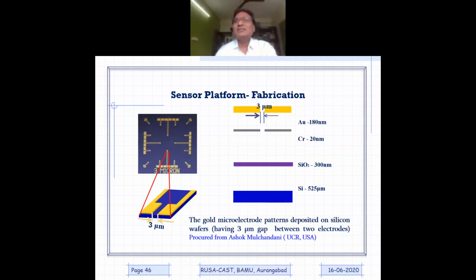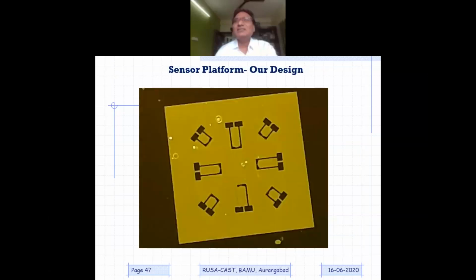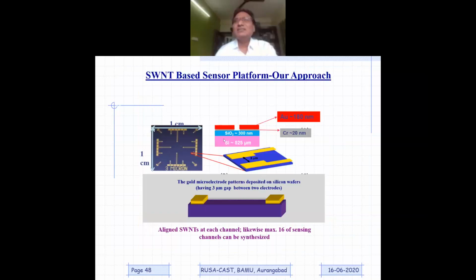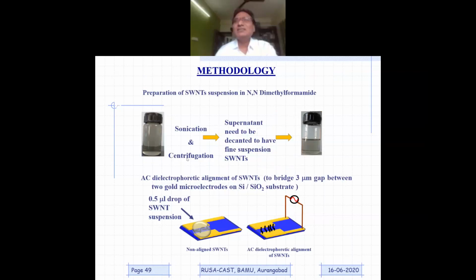Our approach, which we started adopting when I was at UCR with Professor Ashok Mulchandani, because I got rigorous training, as I mentioned earlier, in aligning CNTs by using AC dielectrophoretic alignment. So you can use AC voltage. Of course, you need to optimize the AC frequency, time, and peak to peak voltage to align your CNTs. And I'm sure you cannot have one single CNT bridging the gap, but you are going to have plenty of CNTs bridging the gap.